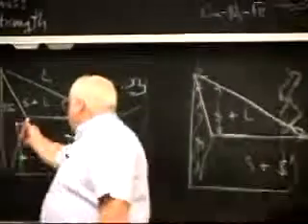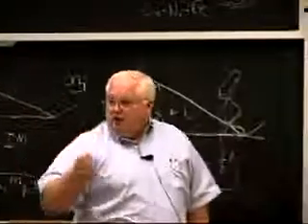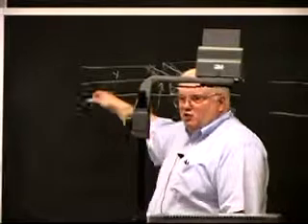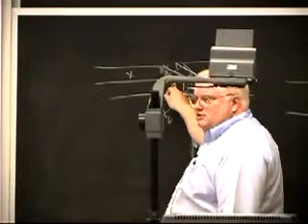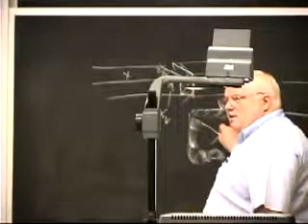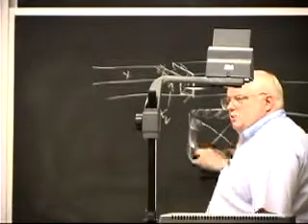Because the heat from welding destroys all this good heat treatment I already did, and I no longer have these precipitates in the heat affected zone, and the heat affected zone is soft. So at first they had lost half their strength, whether the guy used a torch on this or not. The guy who designed this had to have been designing this not for strength, because if he was designing for strength, he wouldn't have welded 6061, not in this type of geometry. Then he wasn't looking for strength here, because he only had about 50% of the cross-section welded.